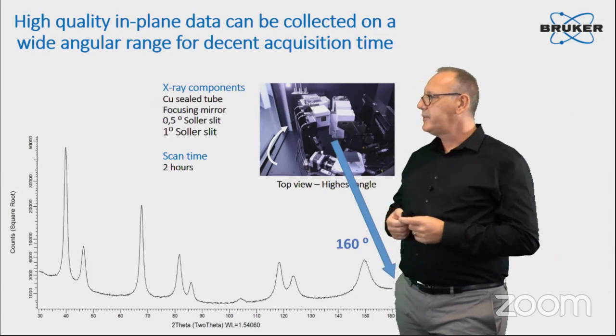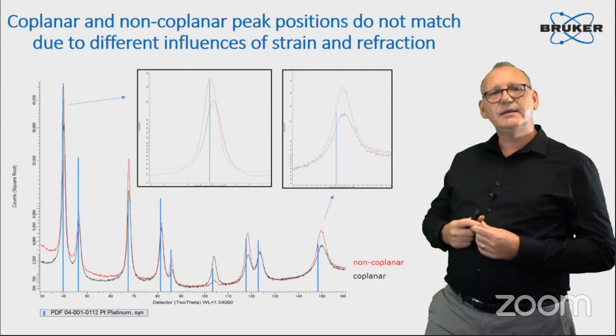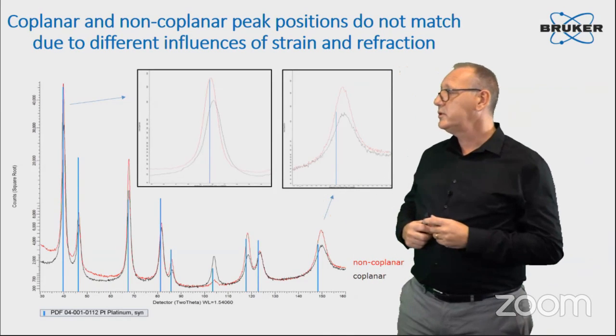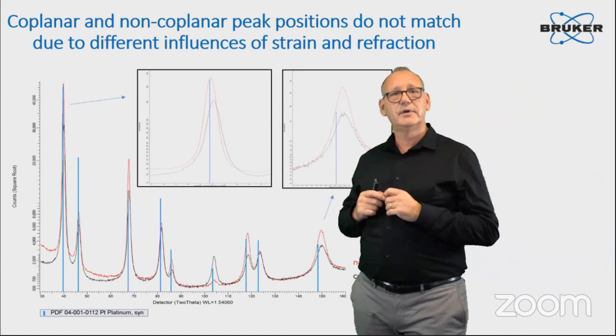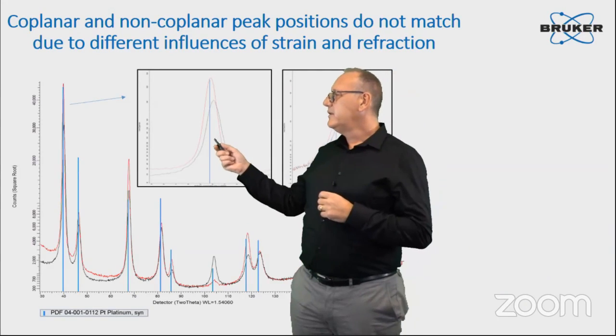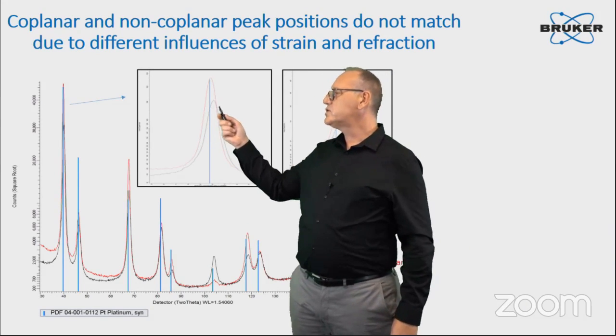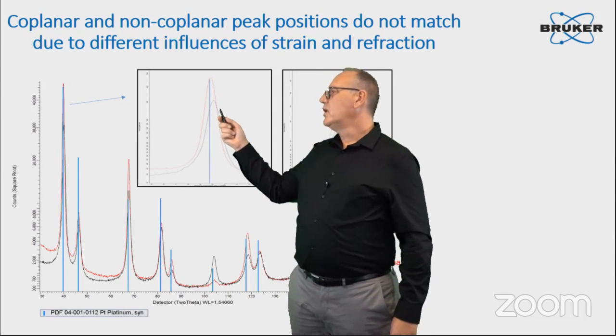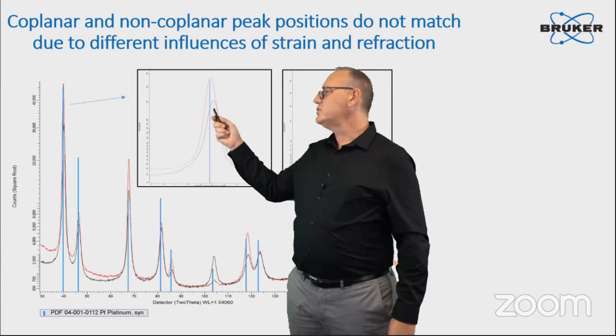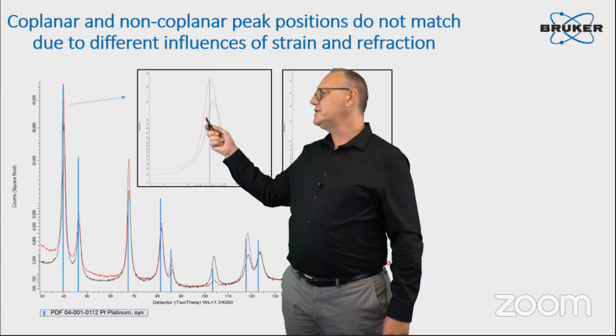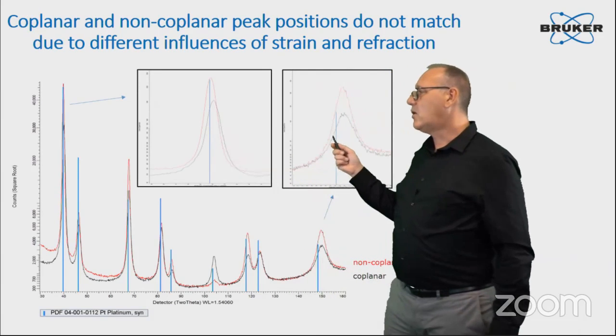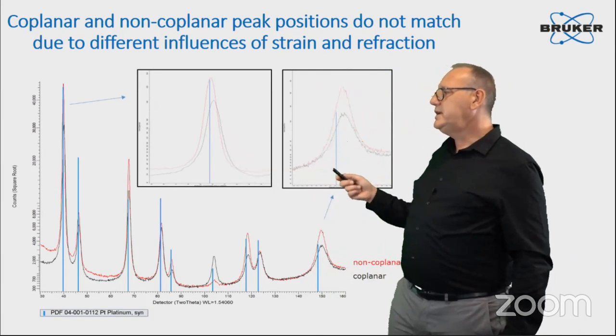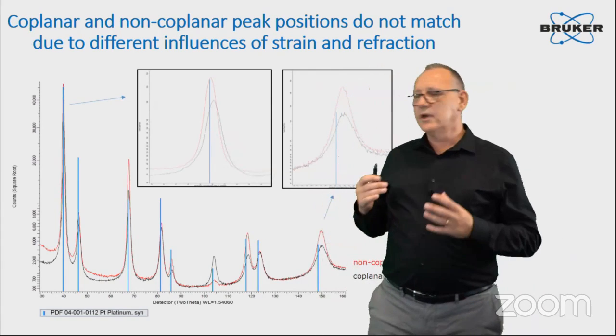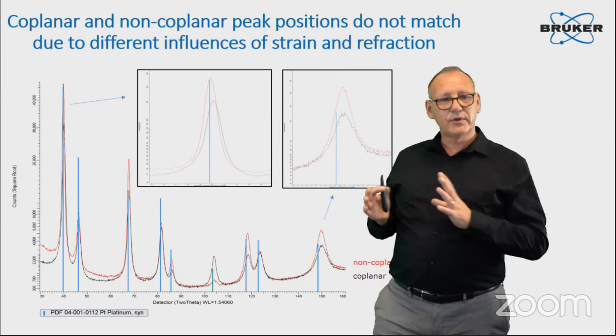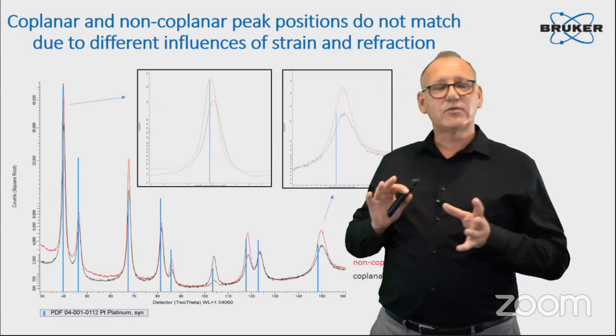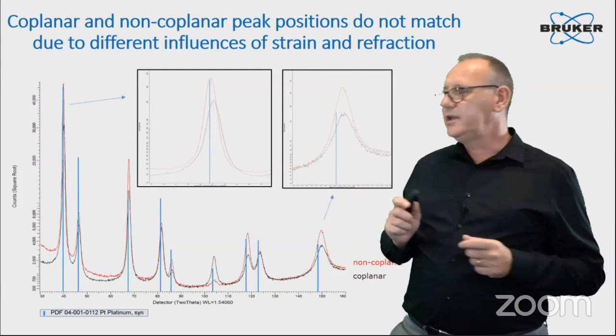So if we just overlap and compare the coplanar GID and the non-coplanar GID measurement, and also compare to the theoretical position of platinum, if we look in detail over the scan, there is basically no peak where we have a good matching of all three. So the coplanar and non-coplanar are at different positions, and the theoretical peak position is also at a different position. If we look at high angle, also, there's a lot of mismatch. So here we need to put a little bit more physics inside to try to understand how come we have different peak positions just by changing the direction of orientation.